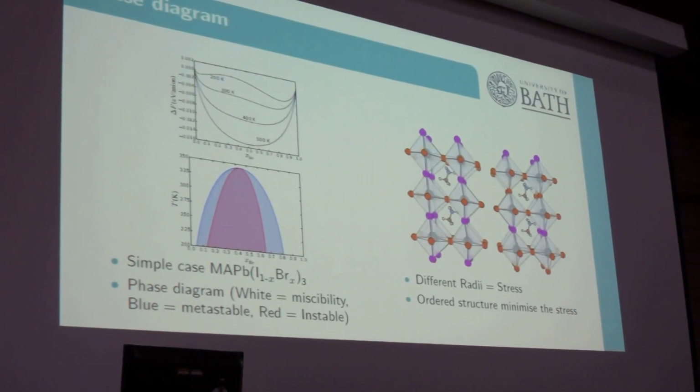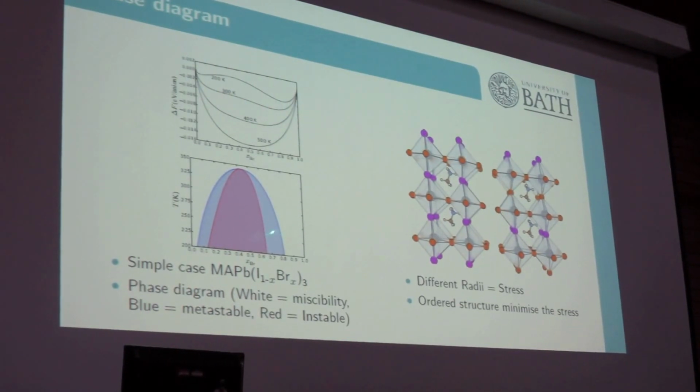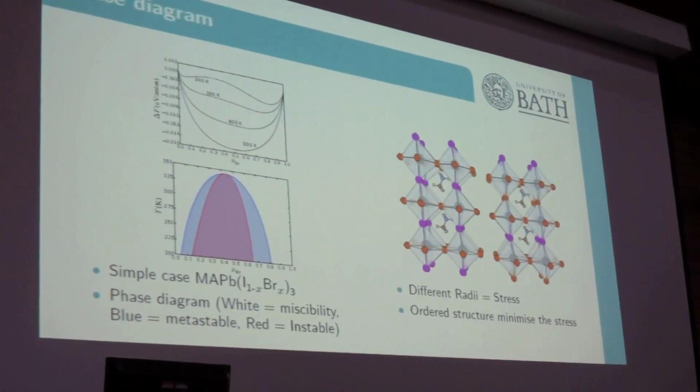The message here is that, first of all, the fact that you have some metastable region means that people can actually synthesize the perovskite in the lab. But then when you do the measurement, the laser heating just disaggregates the material. And that's why there are few experimental data of a certain type for this perovskite.